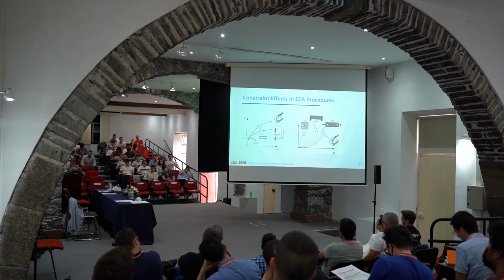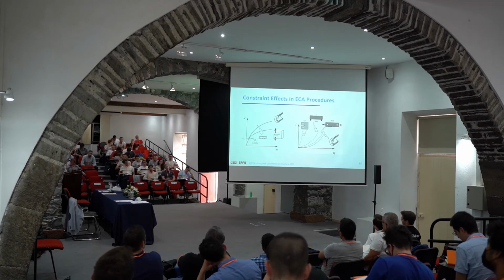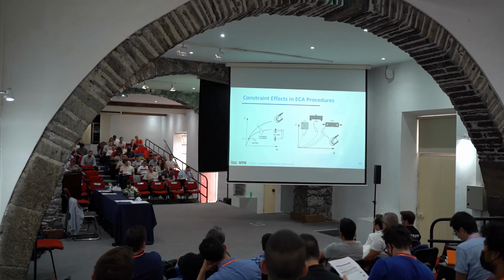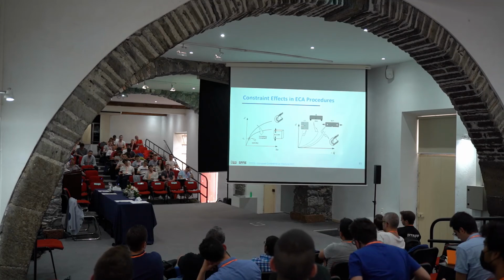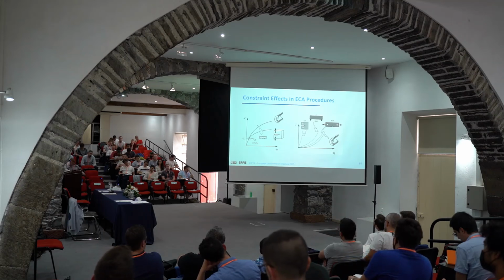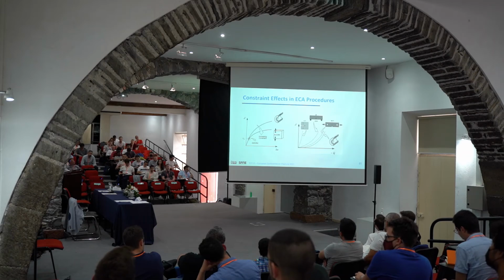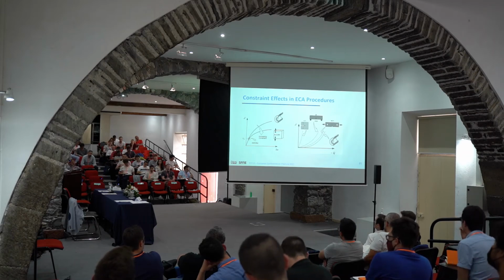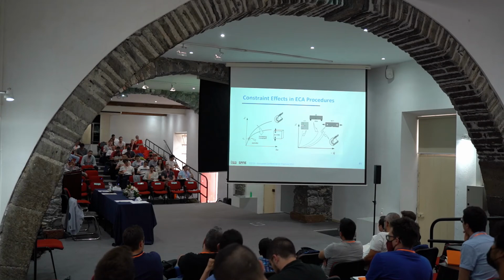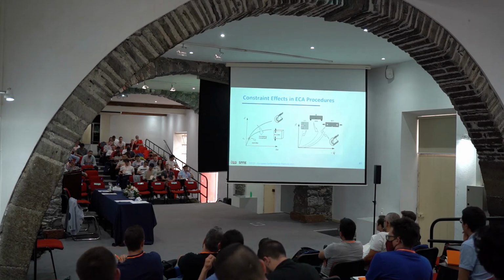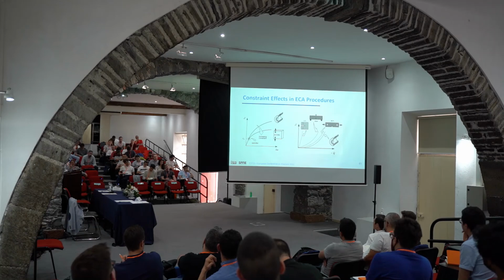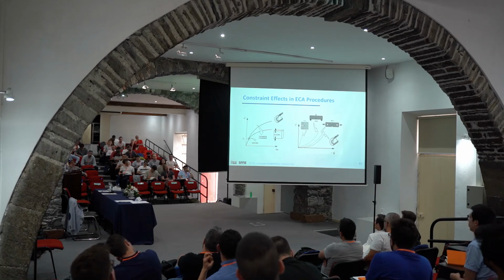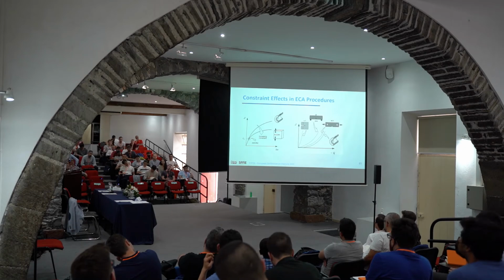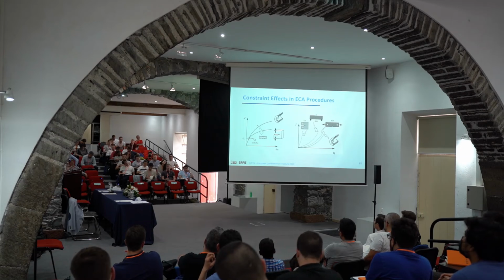the second parameter most widely used is the Q parameter. It describes essentially the difference between the reference solution and the stress field in your actual practical situation. And why is this important? Because this measures what we call the constraint, the effects of constraint. So look at the picture on your right. It's J versus Q. Q is negative, so usually we plot J versus minus Q, just to be more elegant, because Q is the difference here.